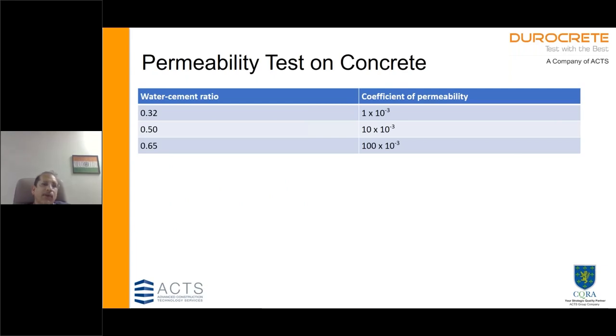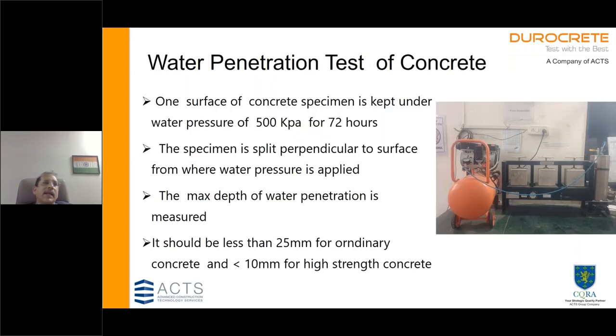So generally it has been found that lower water cement ratios lead to a lower permeability, and you can see here that it is 0.32 water cement ratio versus 0.65 water cement ratio. When you increase, the permeability of concrete has increased 100 times, 100-fold. Fortunately, now IS 516 has given a more easier test that can be easily done, which is the water penetration test of concrete, which you should regularly do as a quality control practice.